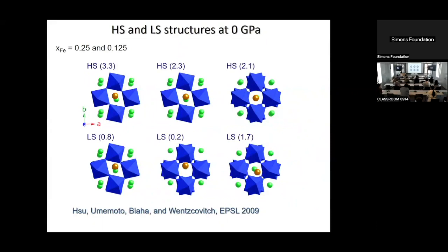But, you know, that's for Earth. If you're studying Mars, it's different. Lower iron at low pressures, even the high pressure form of iron, HCP iron, you can't reproduce. I haven't seen a functional that reproduces the equation of state at low pressures. Above 100 GPa, PBE gets it right. But below, you have